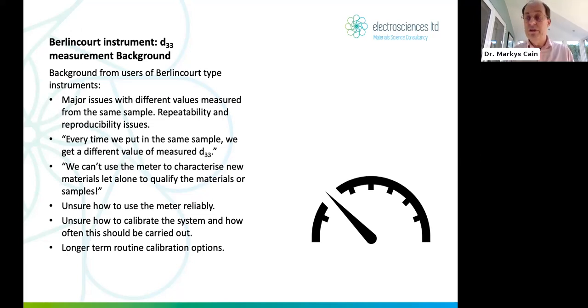You put the sample in once, take it out, put it in again, you get a different answer. I mean, you should get the same answer. The sample hasn't changed, or, you know, has it? I mean, theoretically it hasn't changed, but more of that later. Every time you put the same sample in, we get a different value of measured d33. We can't use the meter to characterize new materials, let alone to qualify the materials or samples.